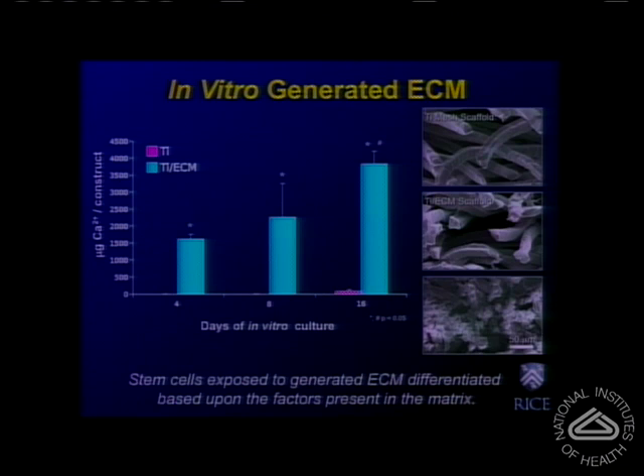We cultured mesenchymal stem cells that were isolated from the marrow of a rat model, and we cultured those cells within the titanium fiber mesh under flow perfusion conditions for a period of 12 days. During that time, the cells differentiated, they produce extracellular matrix, and after 12 days, we decellularize the constructs. So what was left behind was the titanium fiber mesh with a very fine coating on the surface of the titanium mesh.